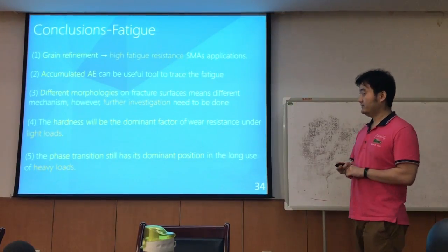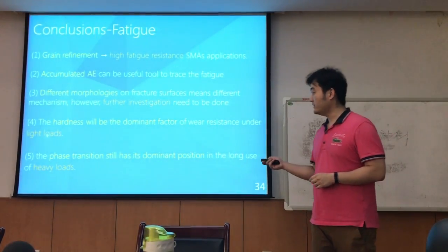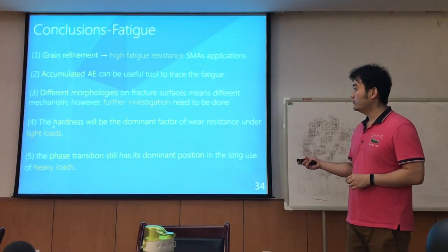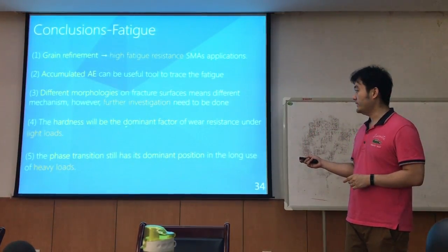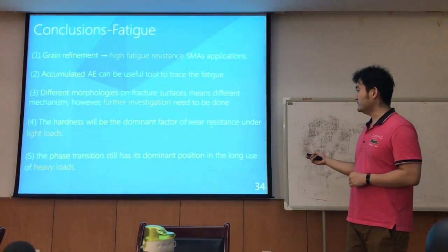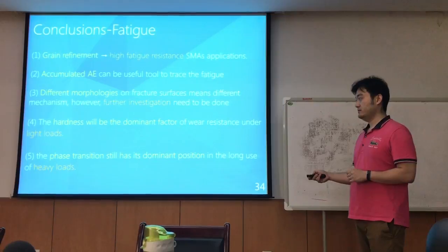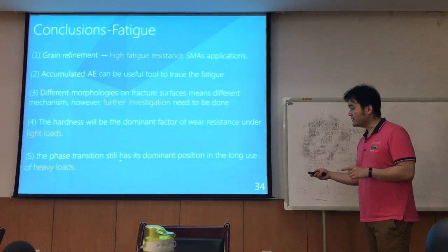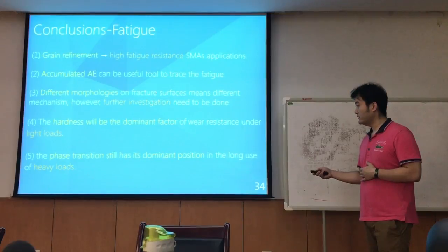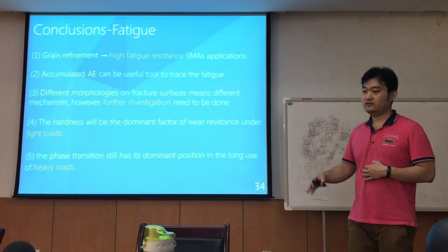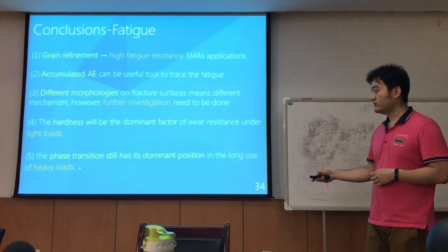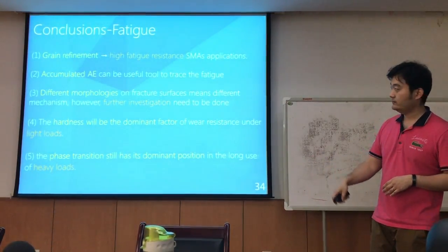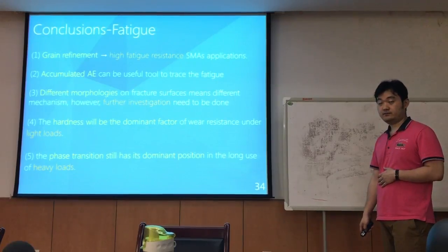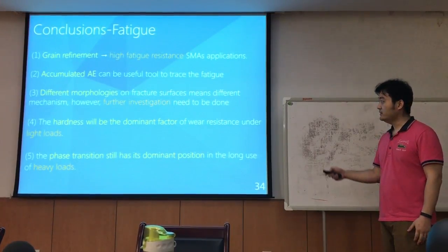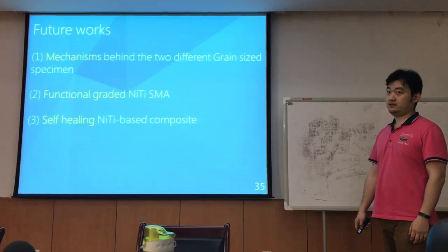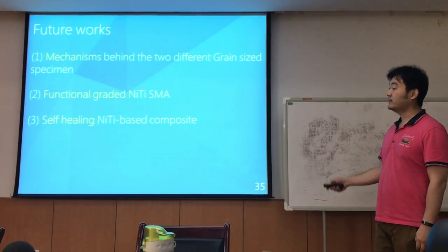thinking is correct. Okay. And the fourth conclusion is for the wear test. We saw that hardness will be the dominant factor of wear resistance under light loads. However, the phase transition still has its dominant position under long use of heavy loads. This is because phase transition will be involved. Okay. So in the future, we need to do some further investigation on the fracture mechanisms behind two different grain size specimens.